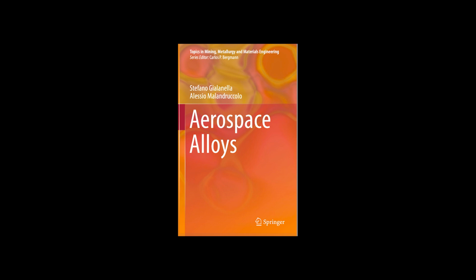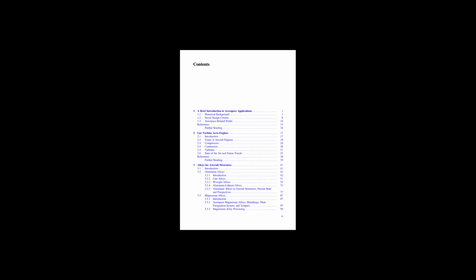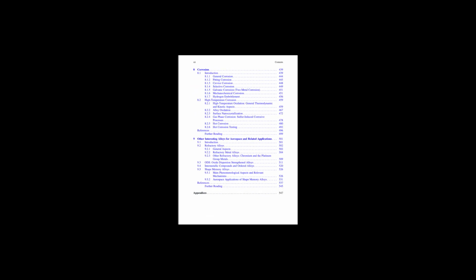Absolutely. For example, with Ti6Al4V, different cooling rates after heating it into the beta or alpha-beta region give you different structures. Slow cooling might give you a coarser, layered structure. Like Widmanstätten. Exactly, that Widmanstätten structure, which can be good for resisting fatigue crack growth. Faster cooling followed by reheating might give you a finer, more interwoven basket weave structure, which often provides a good balance of strength, toughness, and fatigue resistance. So heat treatment is critical. Absolutely critical for titanium alloys.